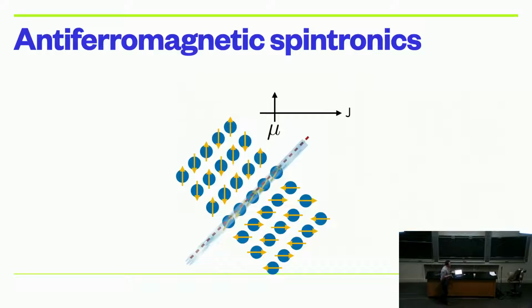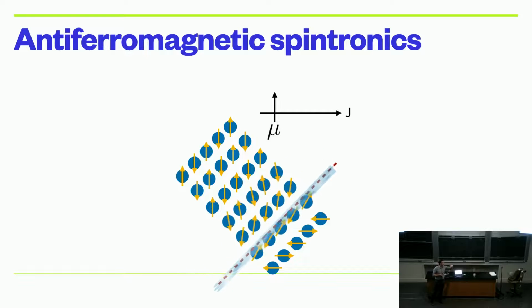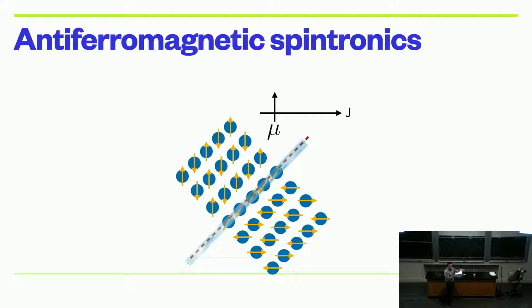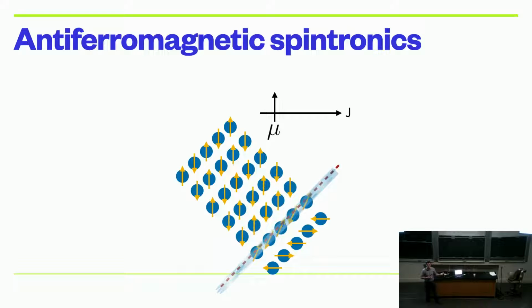So the basic idea is the following. In the system, it turns out, because of symmetry reasons, that when you apply a current, unfortunately also called J here, but it's just a current, it carries a little bit of spin. And that spin can be imparted onto the magnetic lattice. And what that does is that it moves one of these domain boundaries. So that's the cartoon that I've got there. You pulse the current, you flood it with all these electrons that are partially spin polarized, and they can move one of these domain walls.